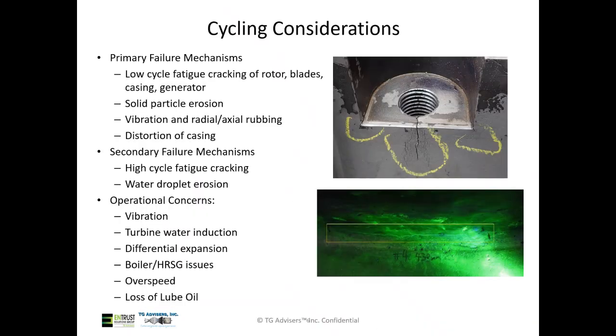So let's start with what failure modes are we concerned with? When we're on-off cycling, we're going from basically no speed up to rated speed, which often is, in the US, 3,600 RPM. Nuclear could be 1,800 RPM, or could be any speed if you have a geared drive. But the point is, you're going from basically standstill up to a speed, and then eventually you're coming back down to standstill. So anything that rotates, that's a significant stress cycle. And you can only do so many of those stress cycles before a crack would initiate.